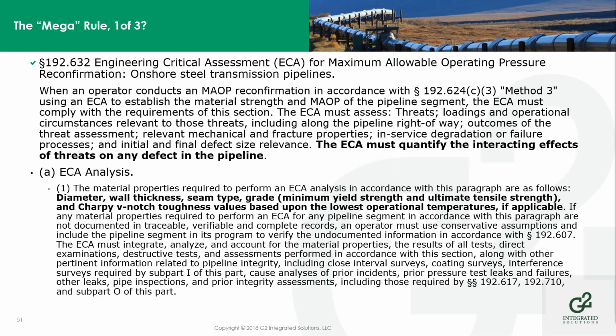For ECA, this is a pretty detailed statement in the regulation now as to what they want done. When you conduct an MAOP reconfirmation, using method 3, using an ECA to establish the material strength and MAOP of the pipeline, it must comply with the requirements of this section. It must assess the threats, the loadings, operational circumstances relative to those threats, including along the pipeline right-of-way, threats, outcomes of the threat assessment, relevant mechanical and fracture properties, in-service degradation or failure processes, and initial and final defect size relevance. This ECA has to quantify those interacting effects of threats on any defect in the pipeline.